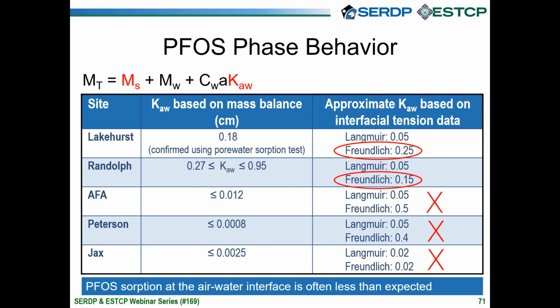There's been a lot of work using interfacial tension combined with various adsorption isotherms, Langmuir or Freundlich, to extrapolate based on field concentrations and the ionic strength of the pore water. We can get a ballpark estimate, and for Lakehurst, the Freundlich isotherm seemed to be a reasonable prediction, though the Langmuir wasn't too far off either. For Randolph, the soil where we saw all that release in the batch experiment, we had a pretty high KAW, again in the ballpark of what we'd predict based on the Freundlich isotherm.